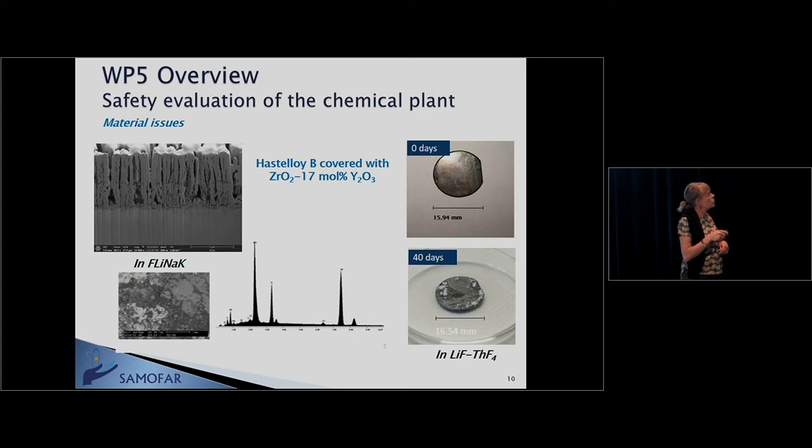We observe the section of the samples. It's very nice. We have a good adherence of the coating, but we observe that the coating has a lot of porosity, so we can imagine that the salt can go into this porosity and attack the alloy. That was observed experimentally, because we observed both in FLiNaK and in the fuel salt dissolution or separation of the layer from the alloy and then an attack of the metals.